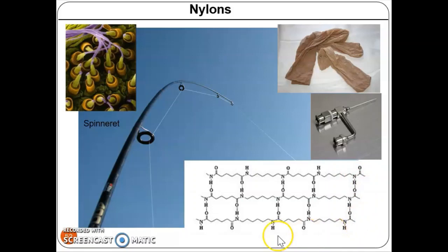To extrude nylon into fibers, scientists got inspired from the spider spinneret, and they produced a polymer spinneret, which is a device used to extrude polymers into fibers by analogy with a spider. How to do this? In fact, scientists take the viscous polymer, meaning we take the nylon and make it molten. Then we exit this polymer via the spinneret into air or liquid to have inversion of phase, which allows the polymer to solidify. Thus, each polymer chain tends to align in the fiber.